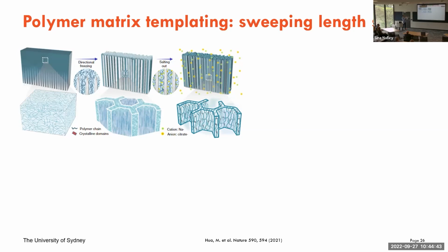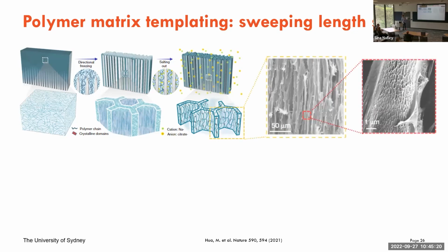In this case, they are using ice crystals and some small molecules to template a matrix, but it doesn't necessarily need to be ice crystals. This is just a concept to show how orienting polymer chains at the molecular level and then at a higher level could lead to a very heterogeneous and extremely strong material. So in this case, we have a hydrogel. Ice has been introduced, growing from bottom to top in one direction. That can be done actually, producing these alignments, as you can see in the yellow box.